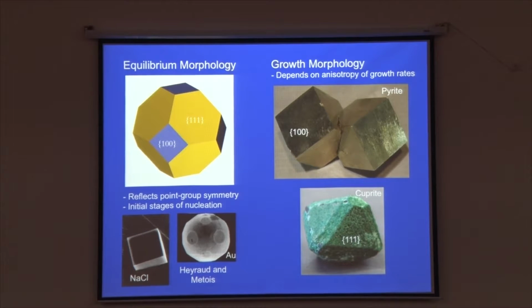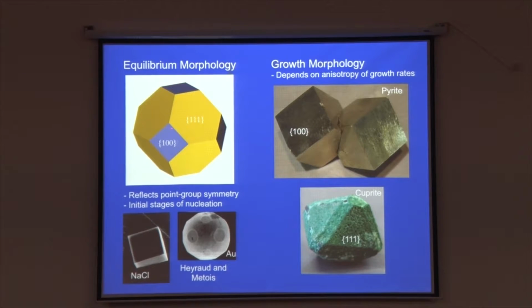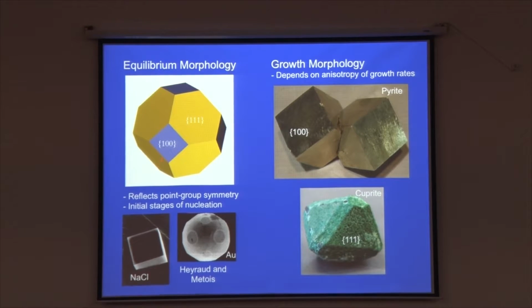We know that for a liquid, of course, this will be a spherical shape, because a liquid is isotropic and has no preference for any specific direction, whereas a crystal is anisotropic, which means that the bond density, if you think about it, is different along different directions. Therefore, the so-called equilibrium shape of a crystal is one that minimizes the surface energy for a given volume of the crystal, and typically for a face-centered cubic material, this is called a cuboctahedral shape. Okay. So, further growth basically happens by attachment of atoms to this nucleus that forms.